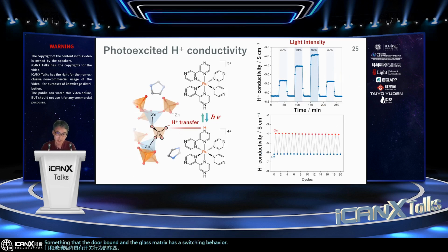So this is like a presumed scheme. This has the MOF glass here, and this has many protons in the structure. But even with a very small amount of the dopant, this ruthenium wants to get the proton from the glass matrix, okay? So this was confirmed by the MLCT changes. And then by applying the UV light on and off, this has a fast switching, which eventually provides the very rapid proton switching, proton conductivity on and off.